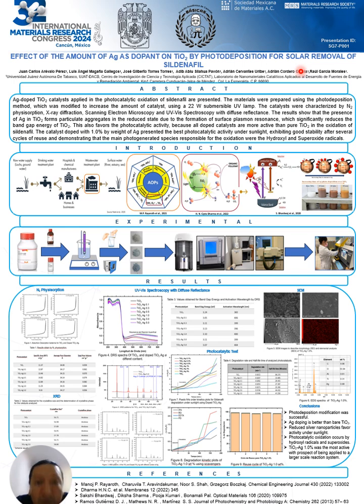The materials were characterized by nitrogen physisorption, XRD, SEM, and UV-Vis with diffuse reflectance. Photocatalytic evaluation was carried out in a solar simulator with a previous adsorption equilibrium between the catalyst and the contaminant. Reaction monitoring was performed by UV-Vis spectroscopy, performing stability tests in reaction with 5 reuse cycles and using scavengers to identify the main photogenerated species responsible for the sildenafil oxidation.